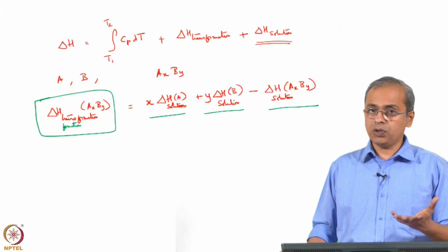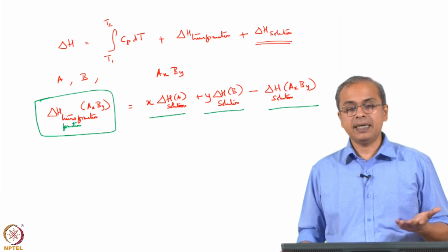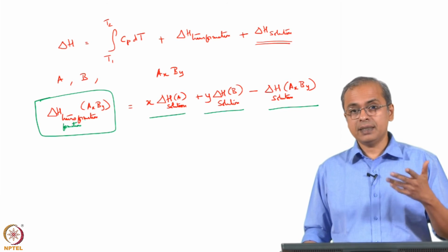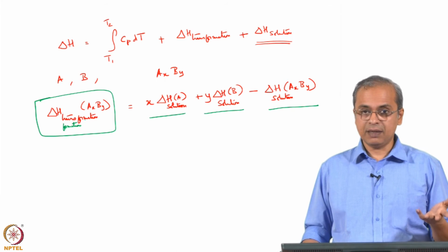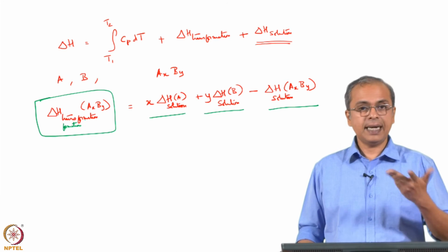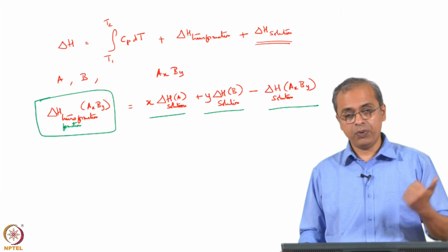One of the things you have to be careful about is that when you do calorimetry at the nanoscale, many materials, because they have high surface area, can be quite reactive, and often they may be hygroscopic. So, they may have pulled in some water.